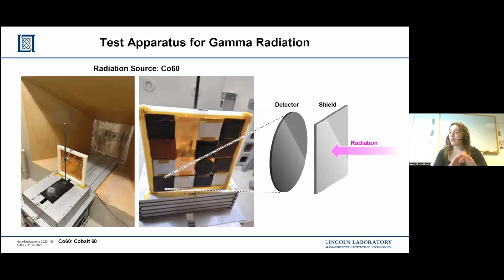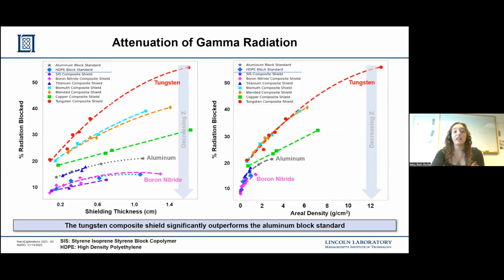So now that we have all the background information, we can actually dive into our radiation testing. For our gamma radiation, we opted to use a cobalt-60 source, and we had this grid set up in the radiation cave where we had a detector behind our shield. We would hit the detector without a shield with radiation and see what the dosage was. And then we'd put our shield in front of it and see what the new reduced dosage is. This allowed us to get our y-axis of percent radiation blocked.